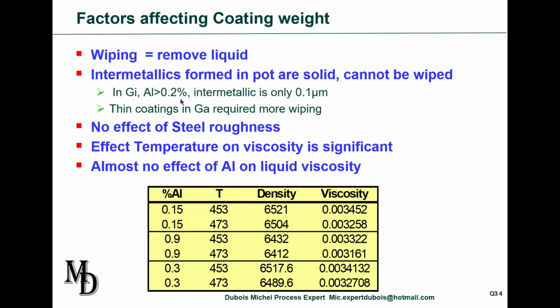But we have to keep in mind that temperature has a significant effect on liquid viscosity, because it's a question of liquid viscosity. I made for you this type of comparison, the effect of aluminum on the viscosity. You can see that a 20 degree difference in the pot temperature changes the viscosity significantly, even more than aluminum does. If you compare 0.15 to 0.3, that's already a big variation in an industrial line. The variation of viscosity for the same temperature is very low.